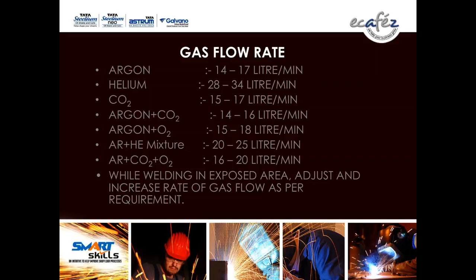CO2, avoid CO2. I repeat, avoid CO2. If you go by CO2 gas, it should be 15 to 17 liters per minute within the workshop. But if you weld in an exposed area by the MIG process using CO2 shielding gas, the rate of gas flow should be more. But I prefer argon plus CO2 in the MIG process for mild steel, for carbon steel. So these are the rates of gas flow.